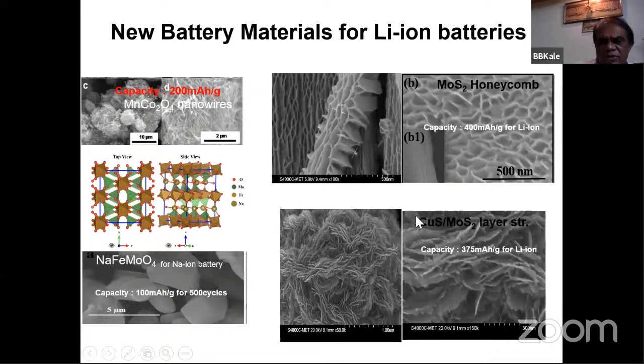Instead of MoS2 alone, we thought whether we could have copper sulfide with MoS2. But we found that if you use copper sulfide together with MoS2 as a heterostructure, this copper sulfide is not very stable like MoS2, and it gets decomposed. This structure is very important, a layer structure we can see here. But the capacity we found is very low, and we observed capacity fading.